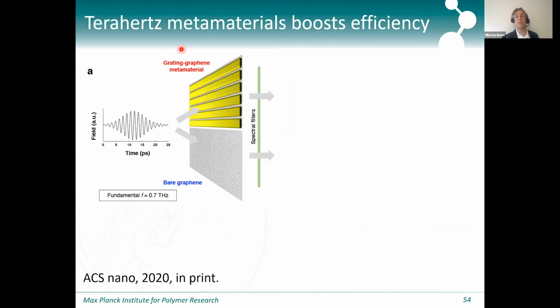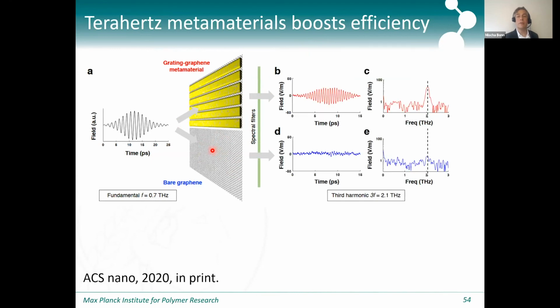So the second thing was to use a terahertz metamaterial, and this was a very simple experiment where we compared putting gold stripes on graphene with no gold stripes on graphene, and then using a spatial filter. You can see that this is for actually very low field strengths, about 20 volts per centimeter. And here you see again the third harmonic. This is at somewhat higher frequency. For pure bare graphene, it's barely above the noise, but for the metamaterial, you can see that it's over an order of magnitude above the noise.